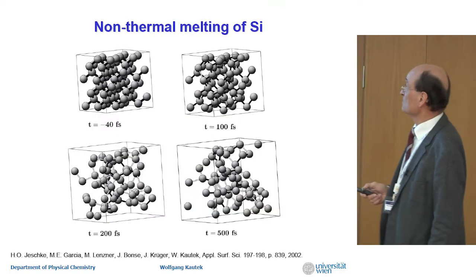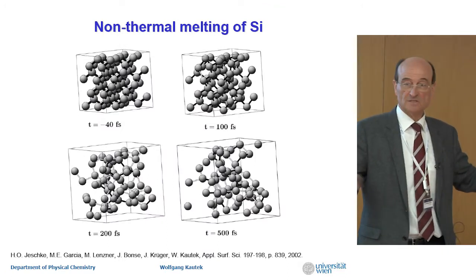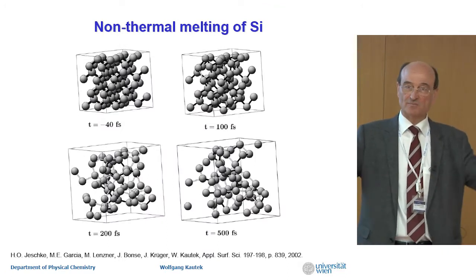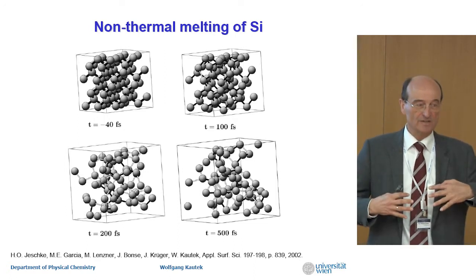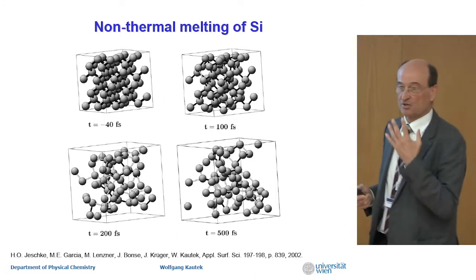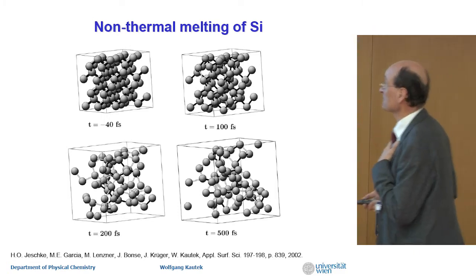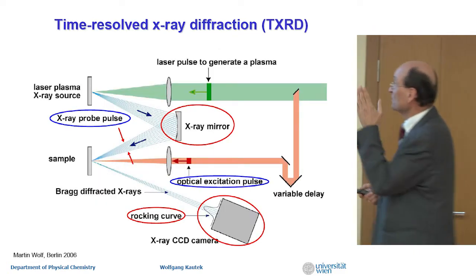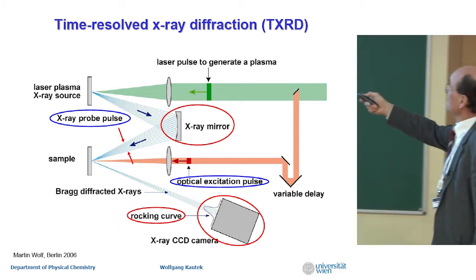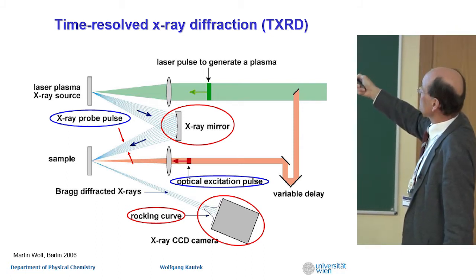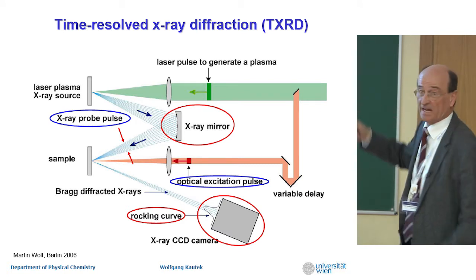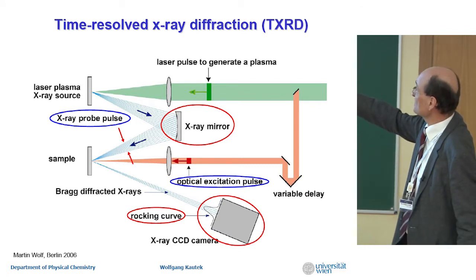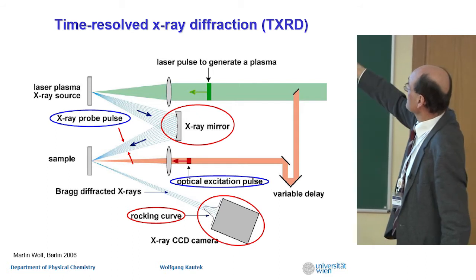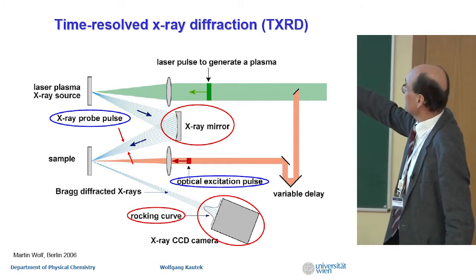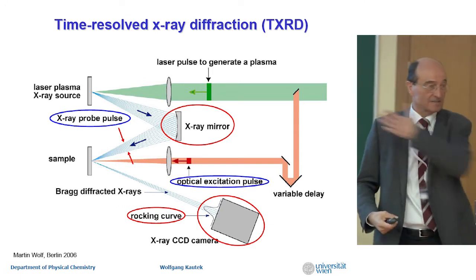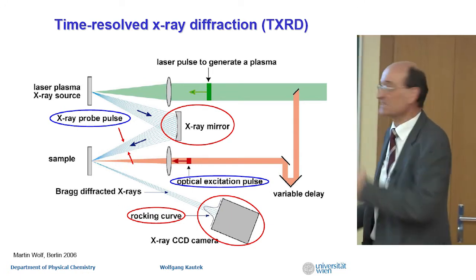And then it freezes again. It returns. So it's not a classical vibrational heating. It's just a softening and then resolidifying. That's the non-thermal melting, we call it. You can prove that in an online setup. For instance, you take a strong laser beam, excite X-rays, yeah? Use this X-ray source to probe the sample, and at the same time, with a time delay, you're using an optical excitation. That's the experiment I just showed you in this Mickey Mouse picture.